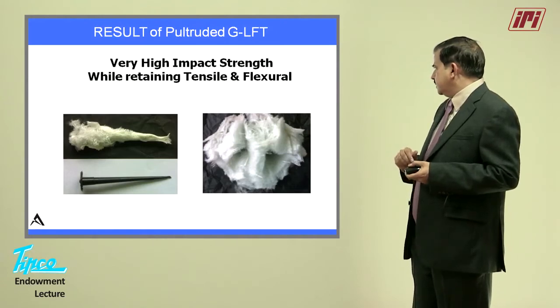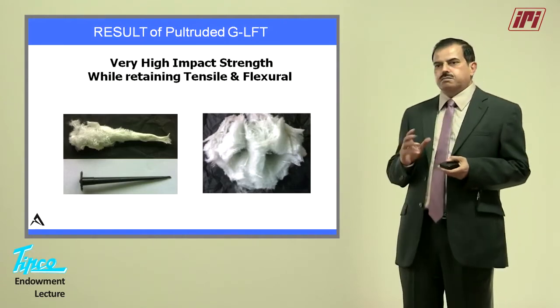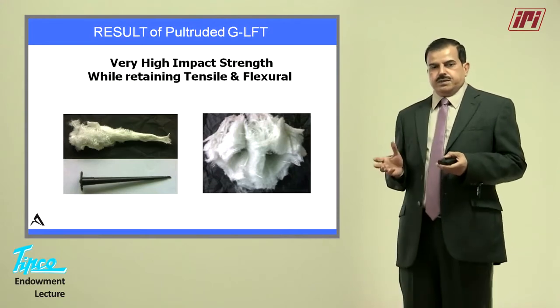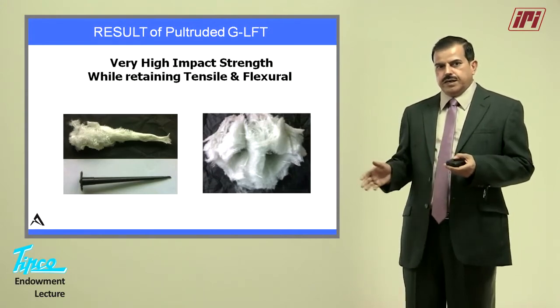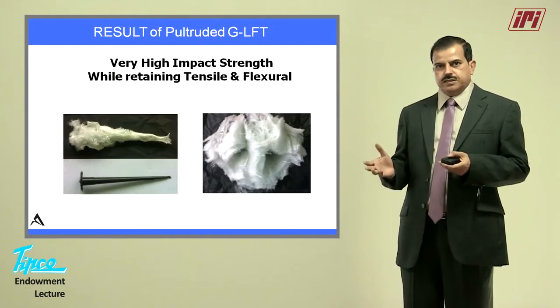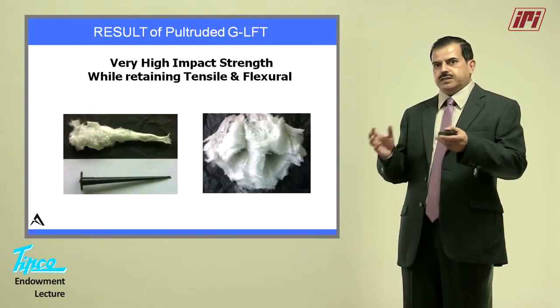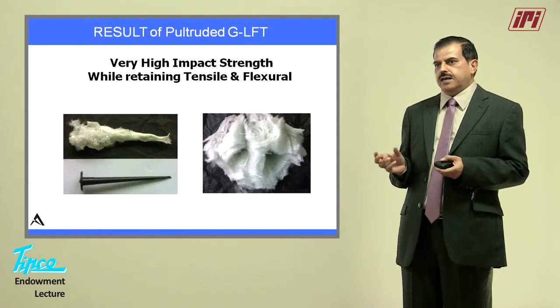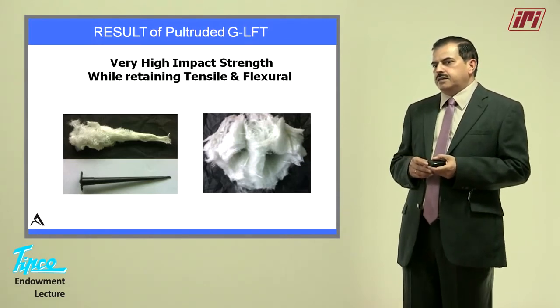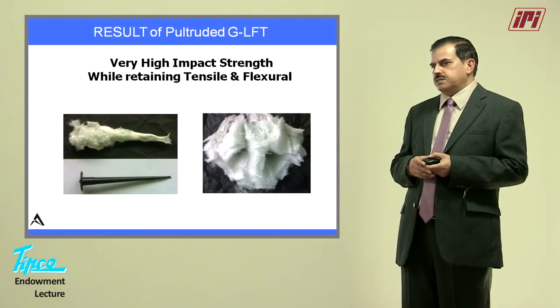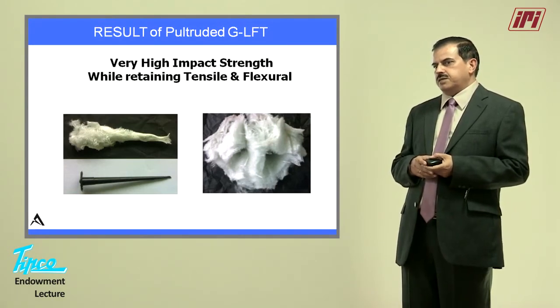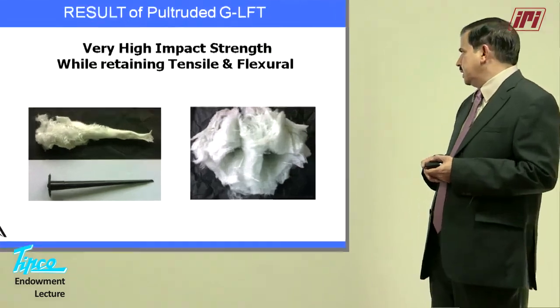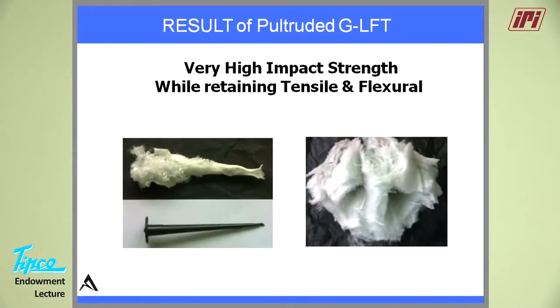This I always say is something very similar to FRP molding, where you lay up the glass fibers and then put resins on it, so you get exactly a very high length of the fibers, and of course you get much better benefits. The only problem with FRP is that the process of laying up is difficult, it is labor intensive, and you can't mold complicated components out of FRP.